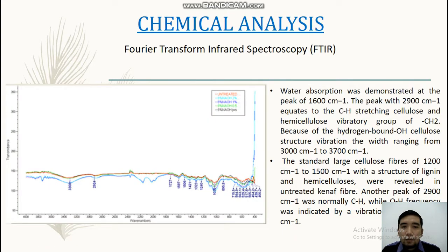Okay. For the chemical analysis, what I get is water absorption was demonstrated at the peak of 1,600 cm. The peak with 2,900 compared to the CH stretching of cellulose and hemicellulose vibration group of CH2, because hydrogen bond OH cellulose structure vibrates widely, ranging from 3,000 to 3,700. The standard of cellulose fiber of 1,200 to 1,500 with structure of lignin and hemicellulose were revealed in the untreated Kenaf fiber.